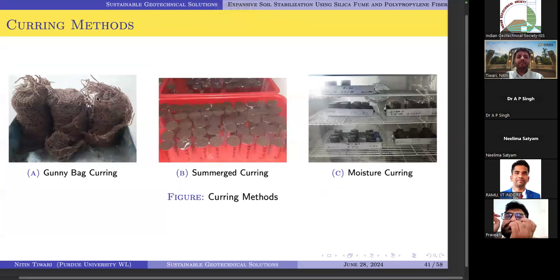When it comes to the curing, we use the gunny bag curing. Gunny bag curing is like a jute bag. So you just wrap your samples inside the gunny bag, keep on providing moisture so they should not be dry, and just do the curing for 7 days, 14 days, and 28 days.